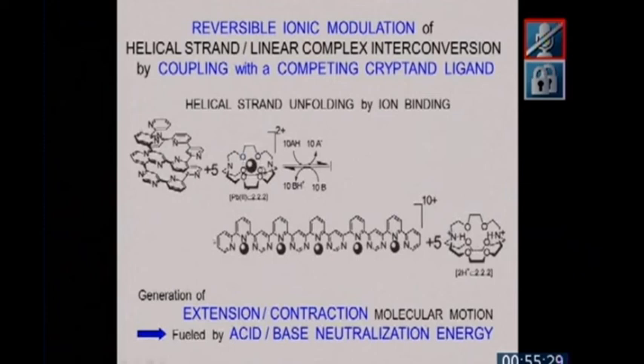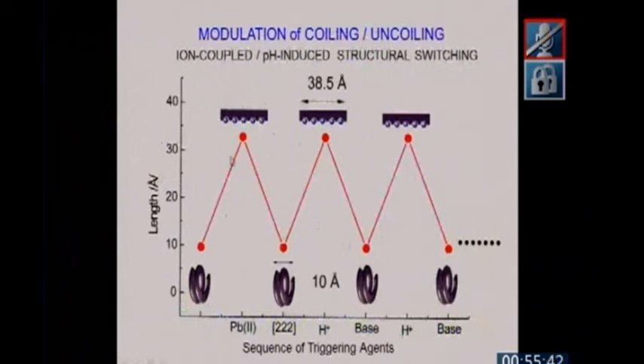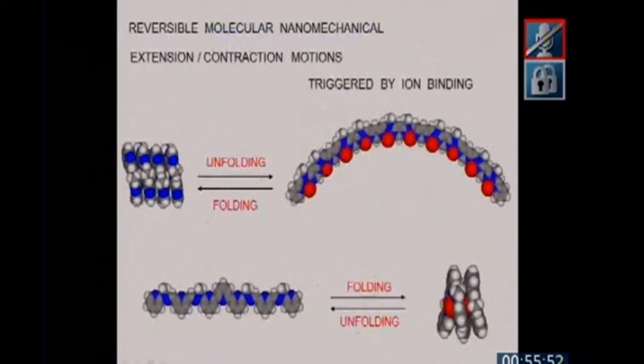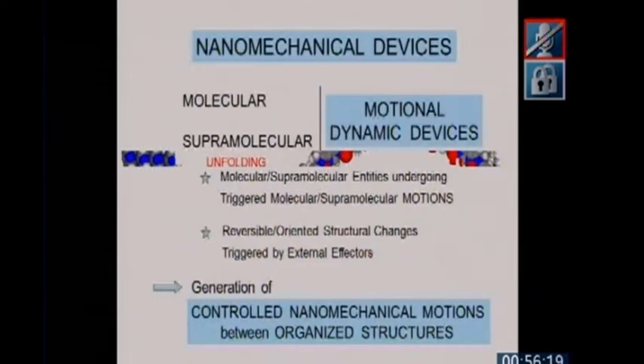So you can reversibly, by adding acid and then adding base, going back and forth, have a sort of extension contraction motion fueled by acid-base neutralization energy. This is represented here: helix, strand, extended strand, helix, strand, and so on. I said that in addition to taking a helix, unfolding it by metal binding, and then folding it back by removing the metal, one can also start with a linear strand. I have not time to get into that. Fold it to bind around metal ions and unfold it by removing the metal. This can be called nanomechanical devices. They are small entities which generate molecular motion of extension contraction type, which is also present in biological molecules, and it's a sort of controlled motion between these organized structures, and they can be called motional dynamic devices.